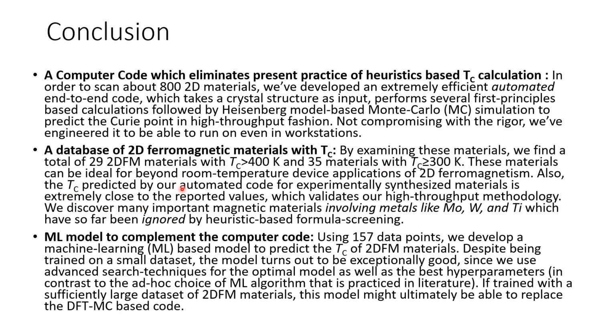The TC predicted by our automated code for experimentally synthesized materials like I've shown you, CrI3, Cr2Ge2Te6, VSe2, MnSe2, is pretty close. Our predicted values using our high throughput code are pretty close to the experimental observations, which validates our high throughput methodology as well. And we discovered many important magnetic materials like metals with low magnetism like MoW and Ti, which have so far been ignored by this kind of heuristic based formula screening.